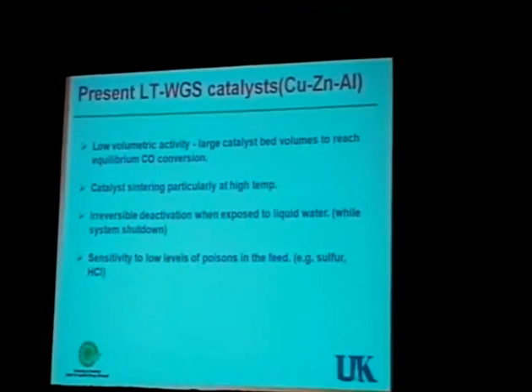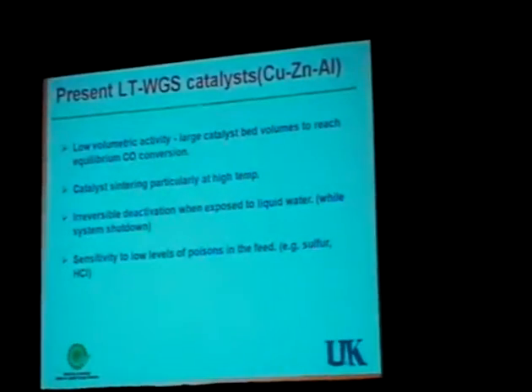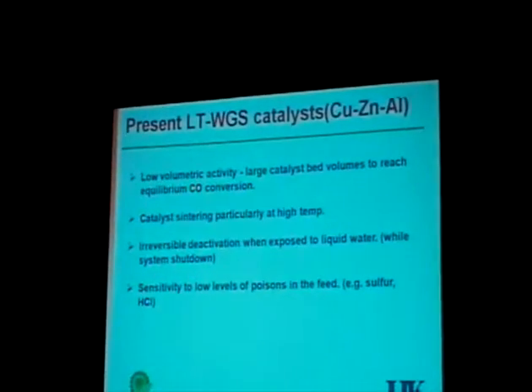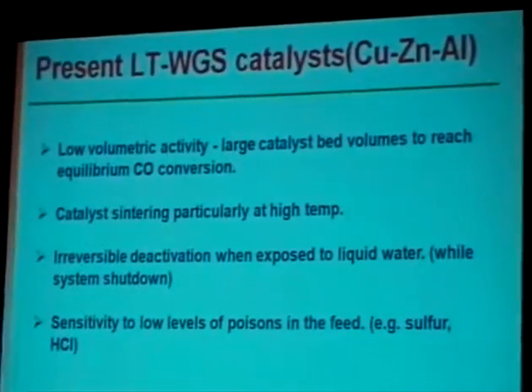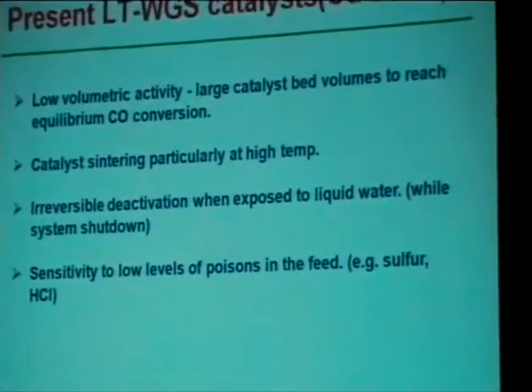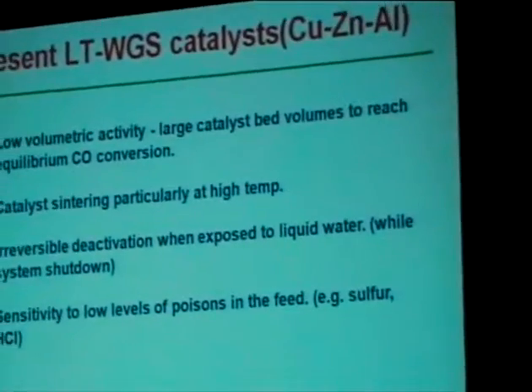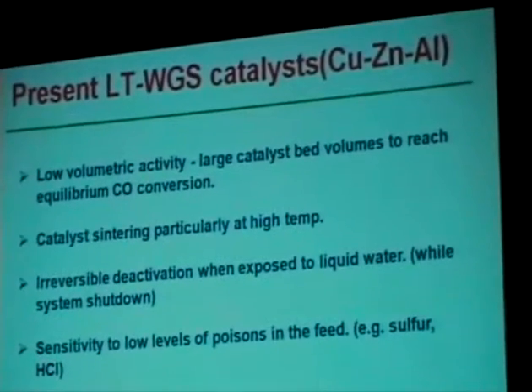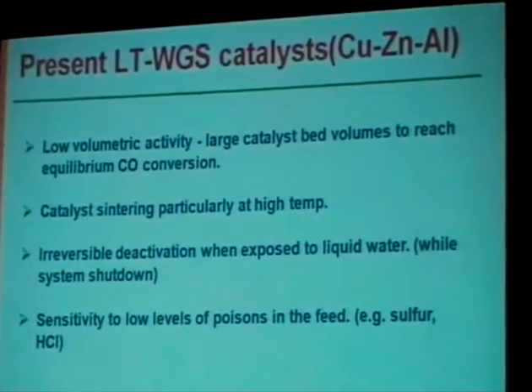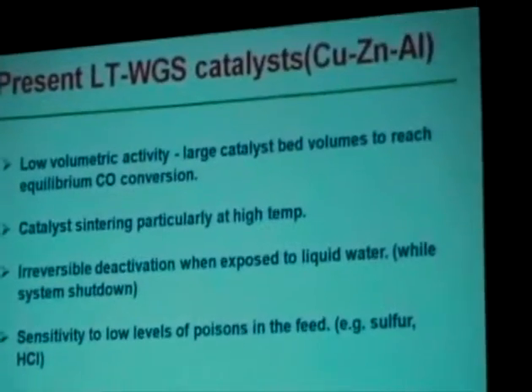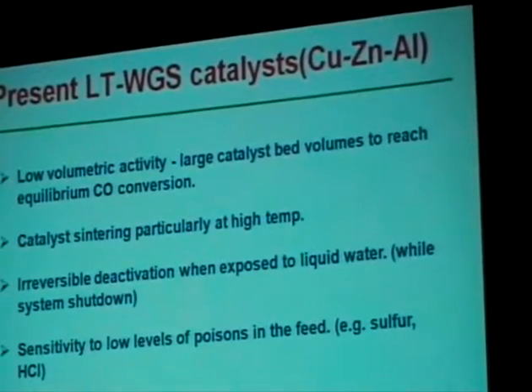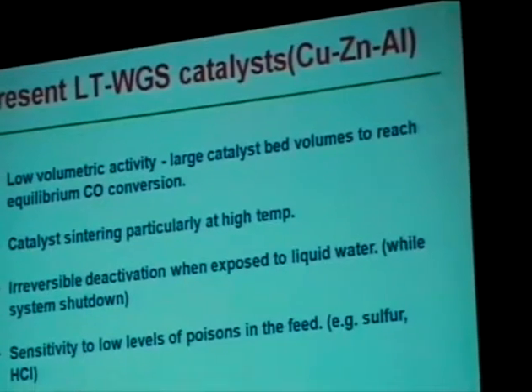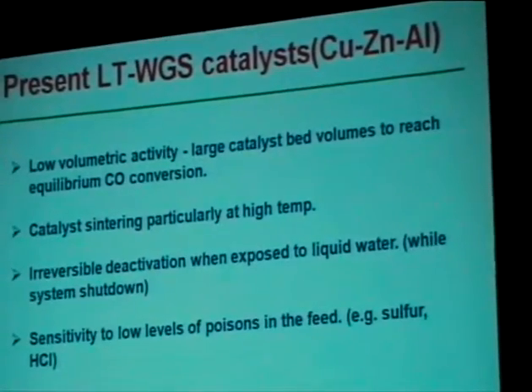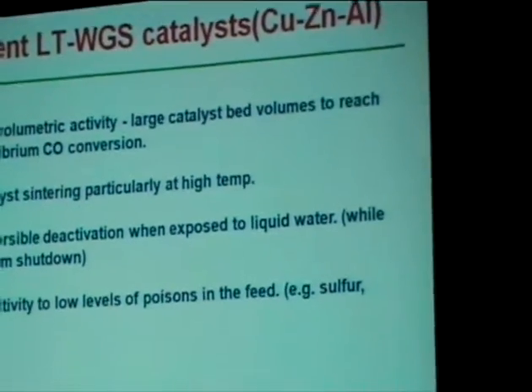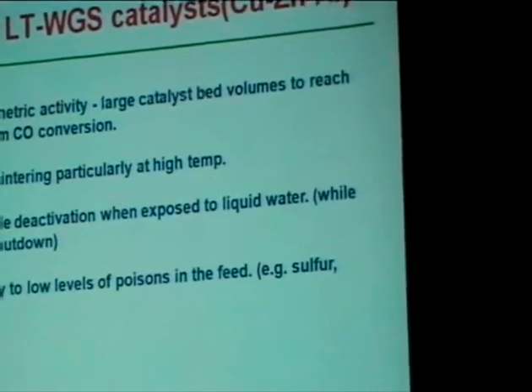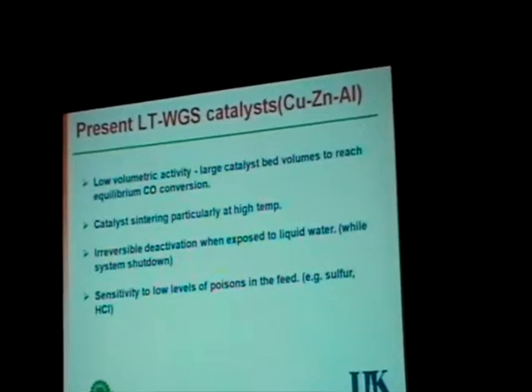the disadvantages or limitations of the present low temperature water gas shift catalyst are, first, the low volumetric activity, which means you need a large catalyst bed in order to reach the equilibrium CO conversion. The second is catalyst sintering, particularly if you operate the catalyst at high temperature. And then there is irreversible deactivation when exposed to liquid water, like when you're shutting down the reactors, or accidentally if liquid water formation occurs, that deactivates the copper, as the copper is oxidizing. Another thing is the sensitivity to low-level poisons present in the syngas, like sulfur and HCl, which need to be removed before processing. So these are the limitations of the present water gas shift catalyst.